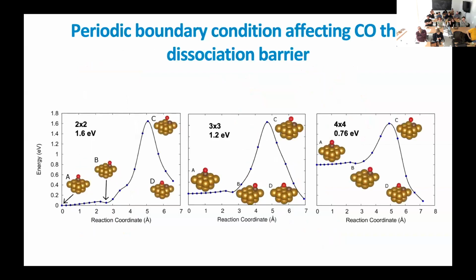And then what I want to show here is that, for example, if I take the 2x2 slab and I try to calculate the nudged elastic band, so we use the nudged elastic band method to calculate the barrier along the entire diffusion pathway for the CO decomposition. And then you see here that we have a barrier of 1.6, and then that barrier actually reduces to 0.76 electron volts if we go for 4x4. So you see, it almost doubles just because the molecule actually interacts with its image due to the finite size effect.